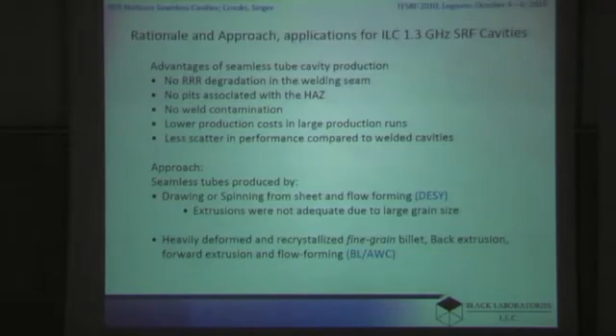The reason we want to use seamless cavities comes from problems in welding of the standard production method. Standard production of niobium cavities from sheet is to deep draw half cells, weld them together, and for an ILC 9-cell cavity, that means at least 17 welds in just producing the cavity before the end groups are added. And whenever you melt niobium, even in a high vacuum, you're inviting problems with impurities. In addition to that, there are issues with pits associated with HAZ, which have caused a lot of cavities to be rejected.